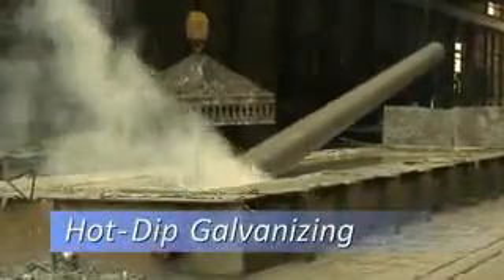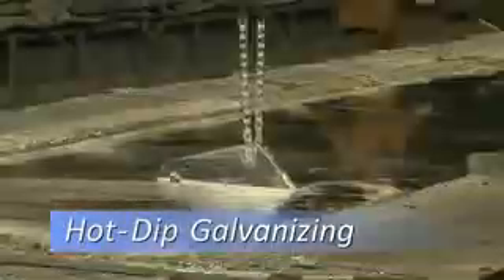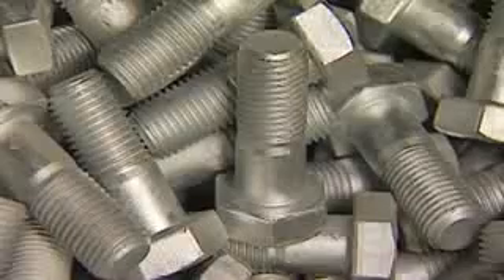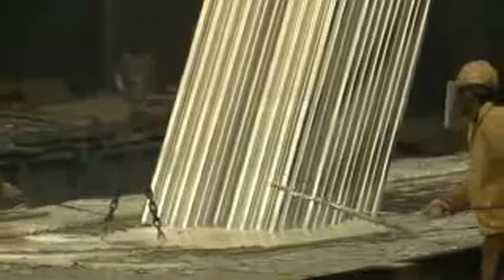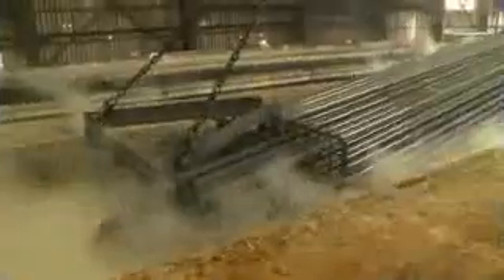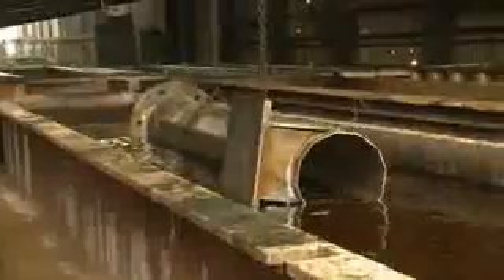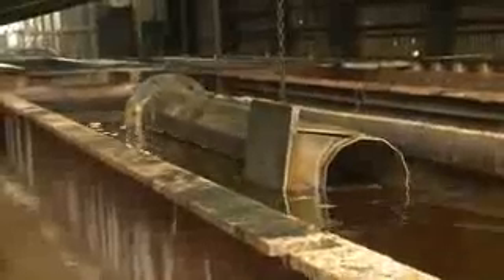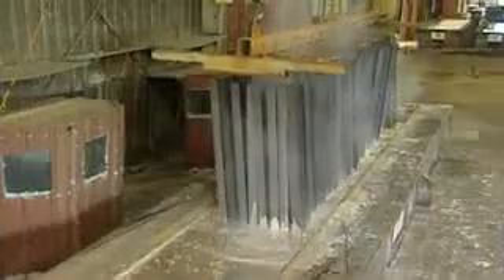Hot-dip galvanizing is the process of immersing fabricated steel into a bath of molten zinc. A wide variety of shapes and sizes can be galvanized, from small nuts and bolts to large structural beams to intricate artistic pieces. Galvanizing facilities are available throughout North America, and steel can be galvanized year-round. Prior to immersion in the zinc kettle, the steel must be chemically cleaned to remove all oil and grease, dirt, mill scale, and oxides. After cleaning and drying, the steel is immersed in the molten zinc.